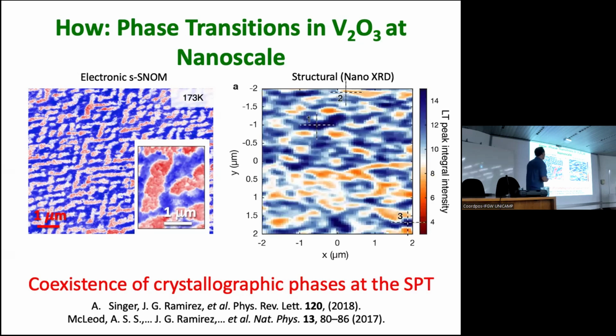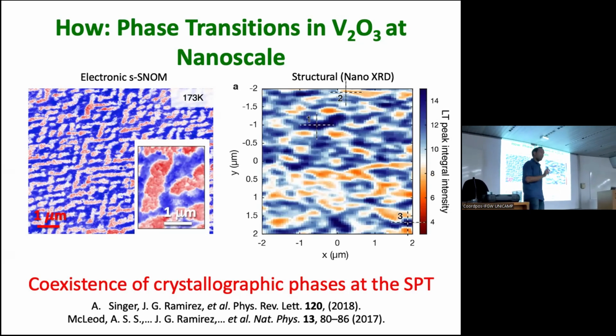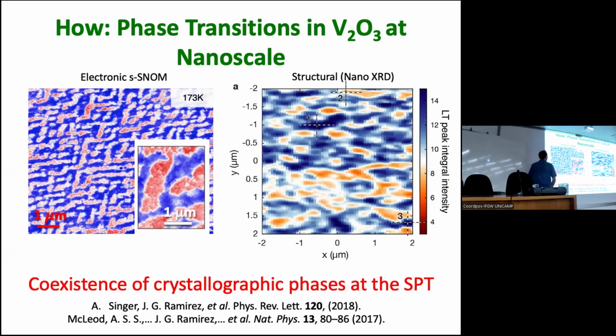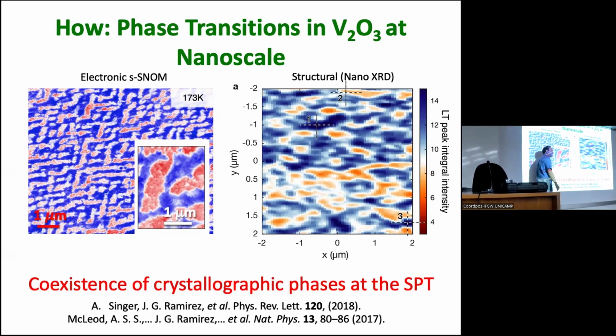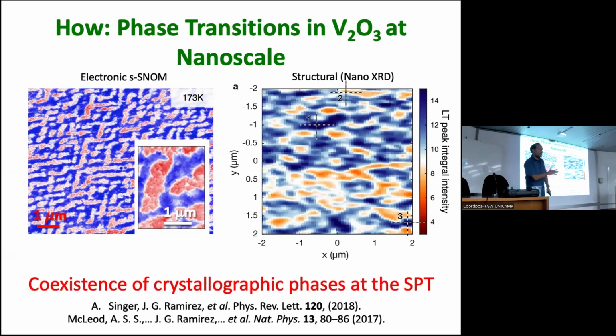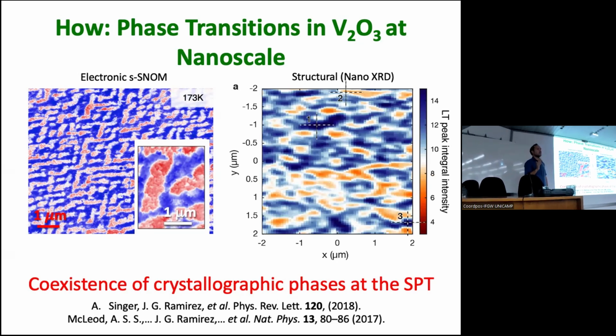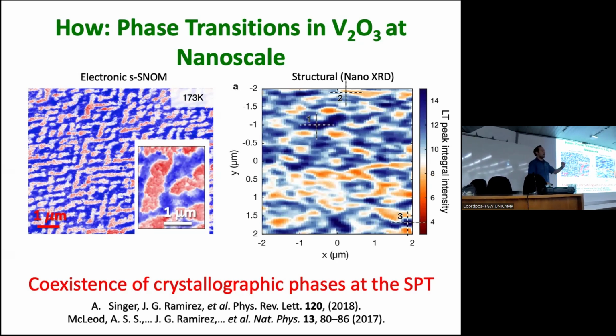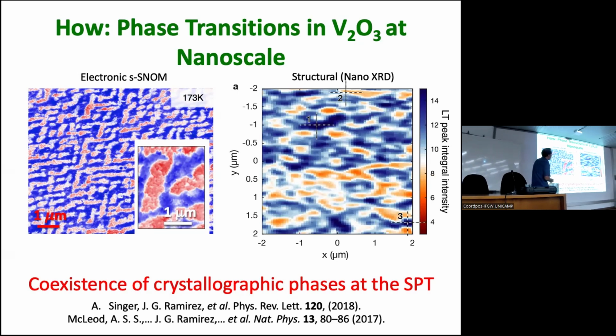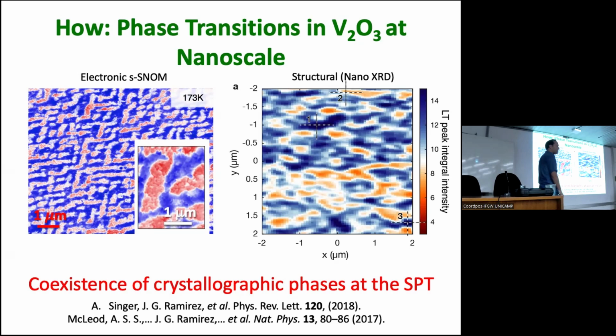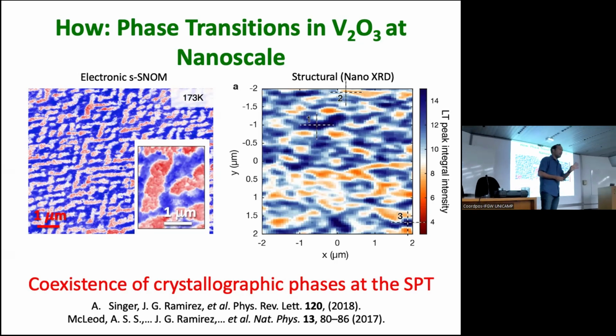But we also did something that is not that easy, and that is to measure the same idea, but with the structure. What I was pursuing is that I wanted to know if in this region, the crystal structure was exactly the structure that corresponds to high temperatures. Okay, so the domains change in size, so we needed a probe that can go to very low pixel size. So we went, recently by the time of the experiment, 2018, and we measured this line at the APS, the synchrotron in the US. And then we measured the structure with a size of 20 by 20 nanometers more or less.